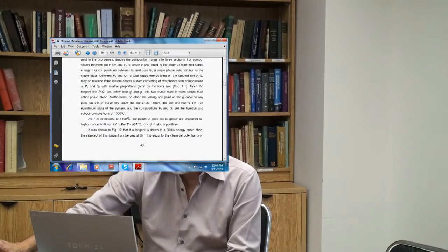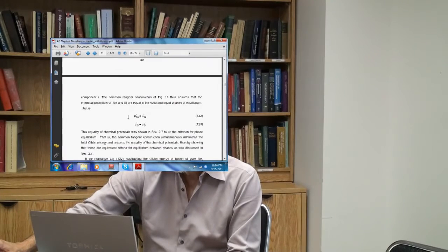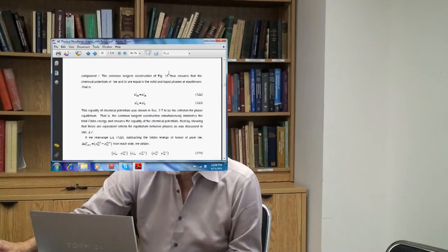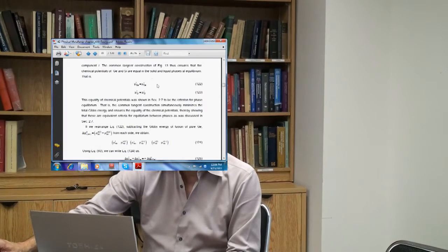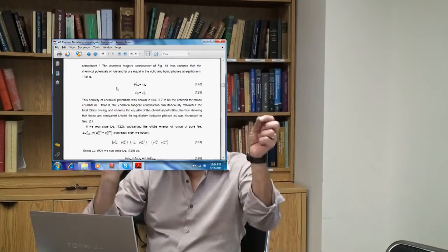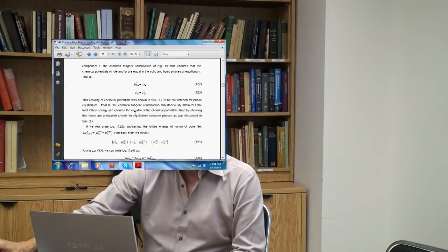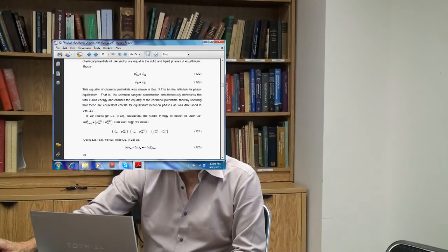Okay, so everything I just said is said here. The common tangent construction assures that the chemical potential is equal, so the chemical potential of germanium in the liquid is equal to the chemical potential of germanium in the solid, on the solidus and liquidus. And that's the criterion for phase equilibrium.